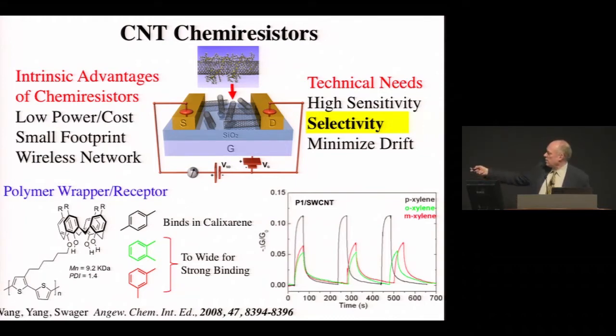And then what you see is after we turn off the gas, there's a desorptive kinetics here. Initially, some of it just comes off, and then we have some that's bound more tightly that has first order dissociative kinetics. And so this is actually quite good. It's actually not trivial to make a sensor that differentiates between xylenes on a molecular basis so simply, because these all have really marginal dipoles. There's just differences in shape, okay?